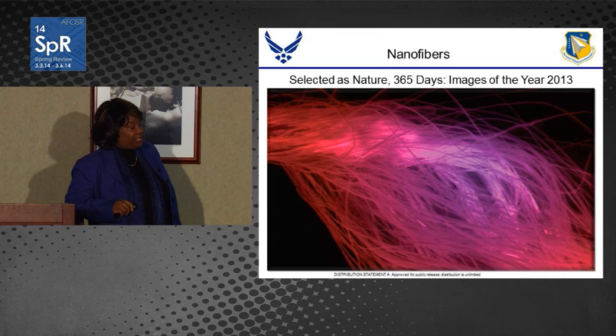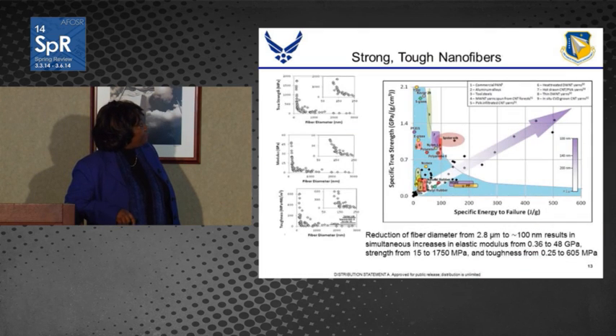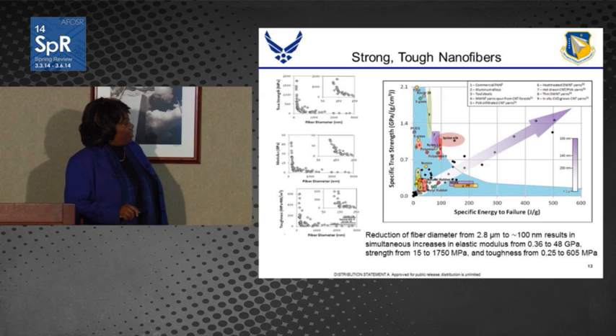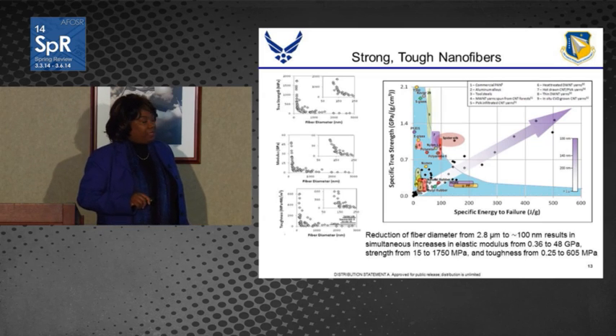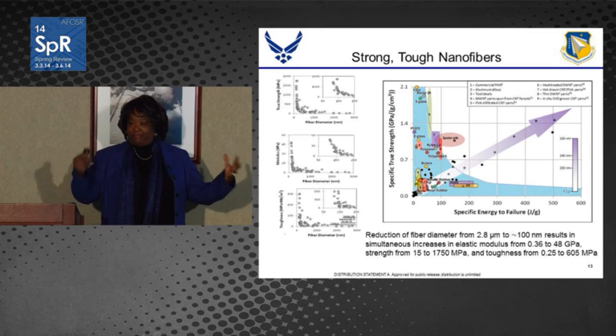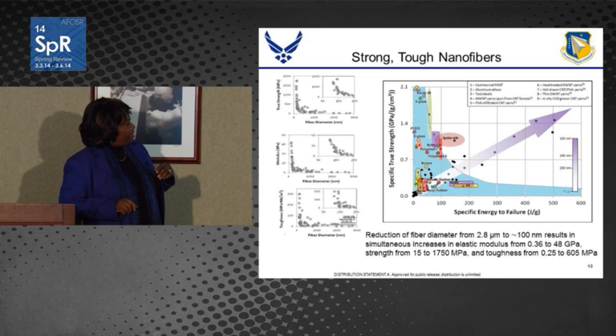And these fibers, what's really interesting and surprising about these is they're not only very strong fibers, but they're also very tough fibers. And so if you look at this Ashby plot, which is kind of an eye chart here, I don't expect you to pay attention to everything on here, but it populates all of the different types of fibers, including down here commercial polyacrylonitrile fibers, spider silk, which Dr. DeLong loves. Up here, everything to something like Kevlar. And the trend you see is that as you get really strong fibers, they're less and less tough, and so the stronger you get, they tend to be more brittle, and so the data kind of goes in this direction.